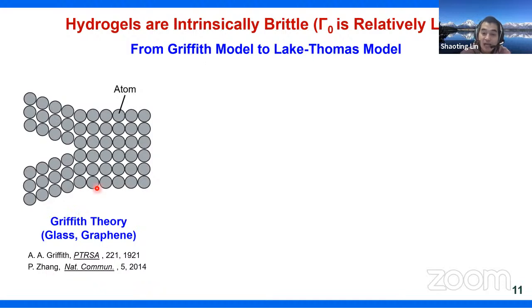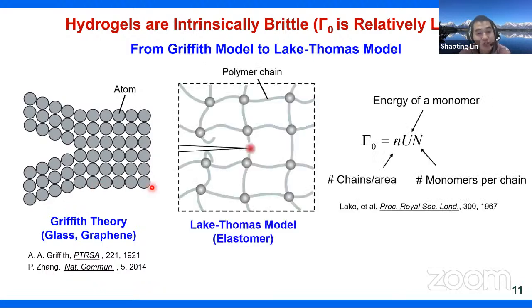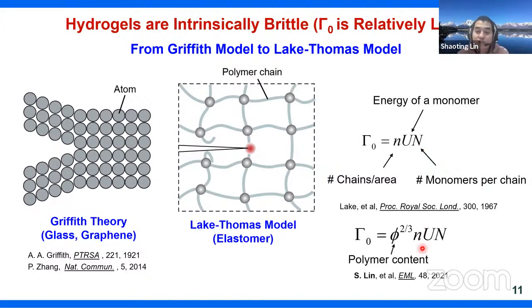But for elastomers, that is different. Instead of fracturing a layer of atomic bonds, the fracture of elastomer is essentially associated with the scission of a layer of polymer chains. Okay, and the intrinsic fracture energy of elastomer will be amplified by capital N times compared with glass or graphene. Here capital N denotes the number of monomers in one polymer chain. Okay, and for hydrogels, due to the low volume fraction of the polymers, the intrinsic fracture energy will be reduced by phi to the power of 2/3. Here phi is the polymer content.